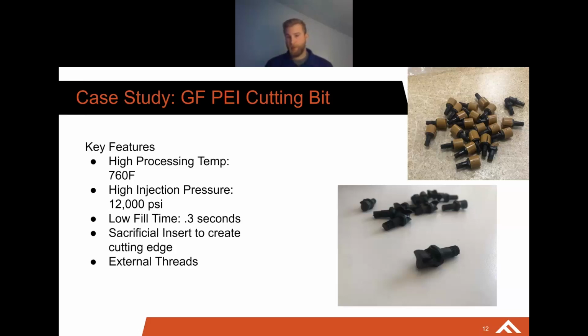Our molds are run at room temperature, so we didn't do any preheating or anything. So in order to get this to not freeze off, I had to be running as fast as it could go. So our fill time was around 0.3 seconds. It is a lot different than our normal 1 to 10 seconds that we usually run. But it worked really well, and I think that this perfectly showcases our ability to run high performance materials as well as really or closer to manufacturing processes.